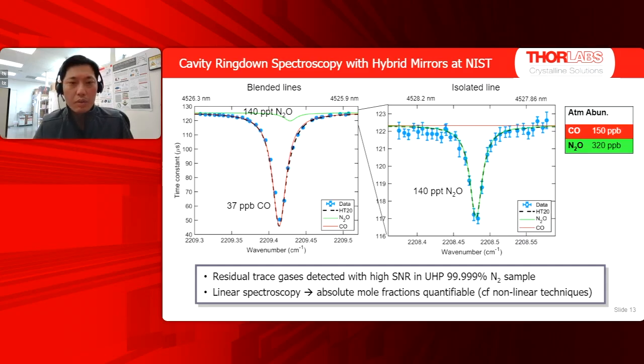And we teamed up with some folks at NIST, some seasoned spectroscopists there. They were interested in looking at process gases and high purity nitrogen. And in this supposedly pure nitrogen sample, they were able to see 37 ppb of CO. And if you look at that trace on the left, you'll see that the CO line doesn't fully explain the measured dots, and there's a little shoulder and deviation from the red predicted trace for CO just to the right there. And that's actually attributable to 140 ppt of N2O.